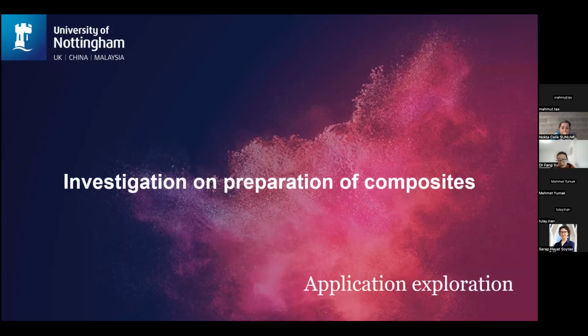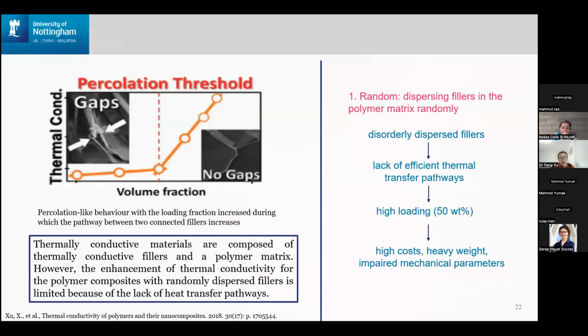I'm going to talk a little bit more about the background or research rationale on how we choose our method to prepare the composites. Normally for thermally conducting composites, we add thermally conducting fillers into a matrix, so those composites are composed of thermally conductive filler and the polymer matrix. However, the result is not very satisfying because the enhancement is not as expected, as there is a lack of heat transfer pathways.